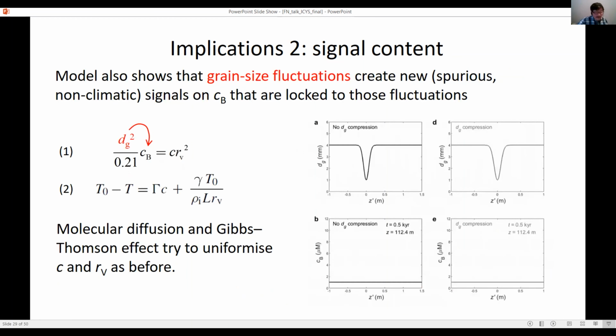One more thing I want to show you, I've just squeezed this in. The model actually shows an additional interesting result when short-scale grain size fluctuations are there in the core. It turns out that when you use those fluctuations to drive the model, new signals spontaneously appear. So on the right are a couple of simulations. Here is grain size. Uniform grains, a piece of ice, uniform grain size, except for a decimeter or so, there's a much finer grain size. In this experiment, we just let that signal descend towards the bed uncompressed.